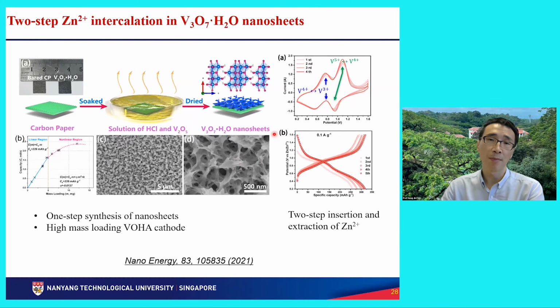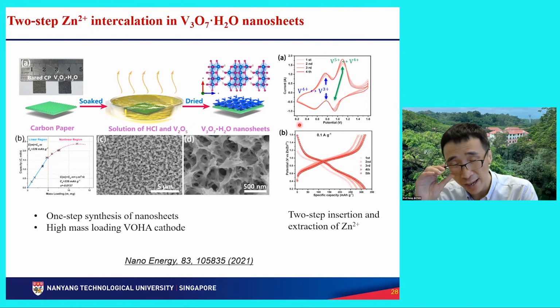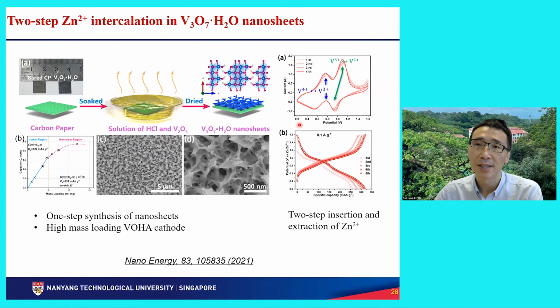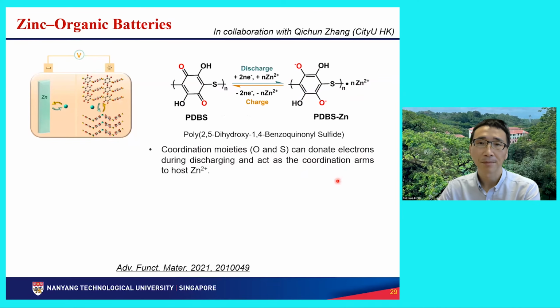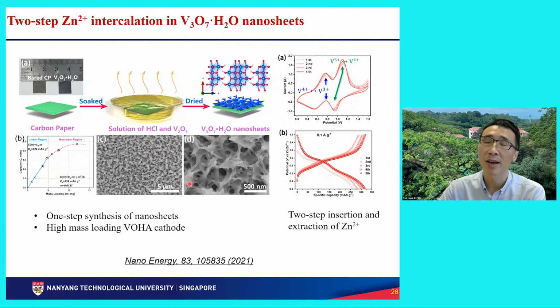And the main achievement of this work is that we use intensive characterization tools to reveal the reaction mechanisms, how zinc ions go in and out of the lattice. We have both in situ characterization and DFT calculations to reveal that there's a 2-stage redox reaction, vanadium 5 to vanadium 4, vanadium 4 to vanadium 3, to give double peaks. Also it gives double discharge plateaus of the full batteries. Okay. This also leads to zinc organic batteries rather than using inorganic ones, because inorganic is unstable, as I mentioned. After many cycles, they may dissolve.